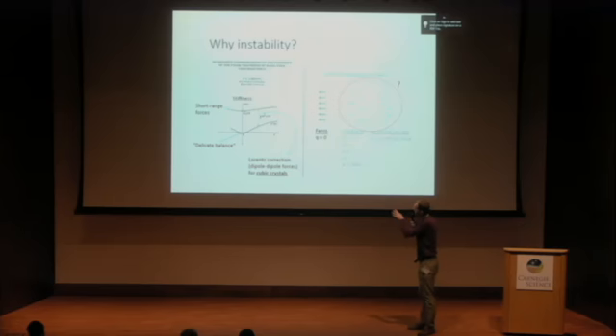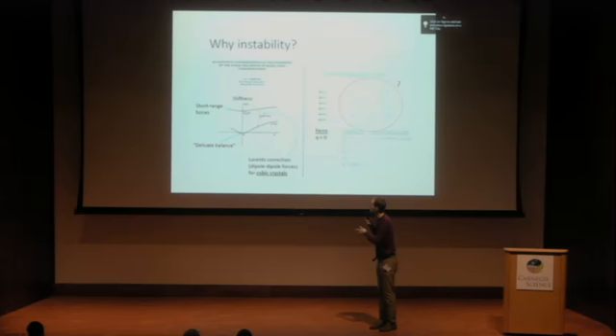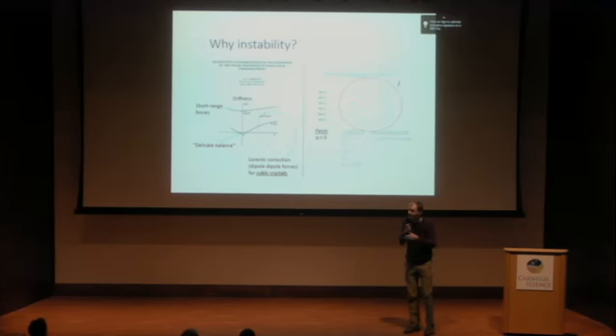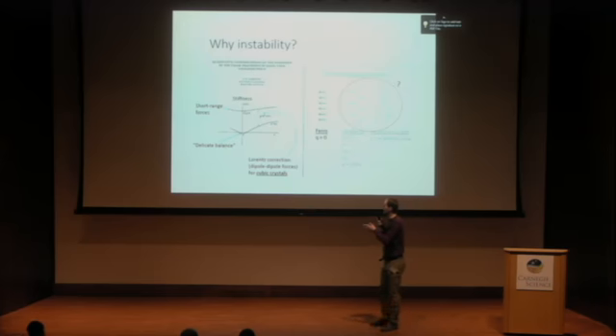This is the paper of Anderson, the soft mode paper, the very famous one. He says there is a wave vector dependence of the stiffness, and there are short-range forces and Coulomb forces, which are competing. The instability occurs as a result of a delicate balance between them. And after 60 years, we still think this way, as is evident from the papers that we publish.